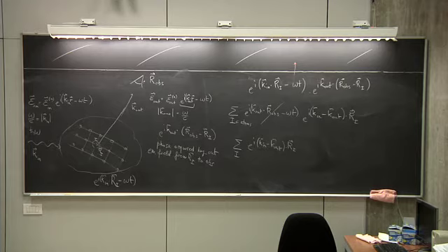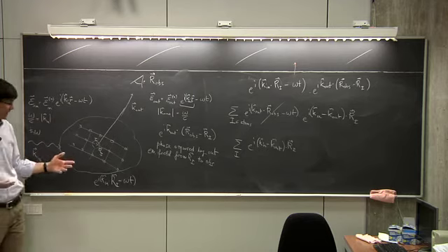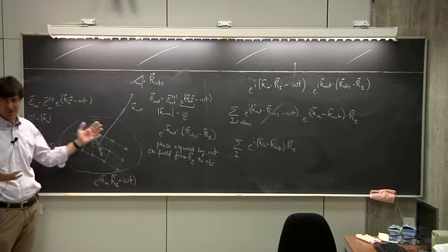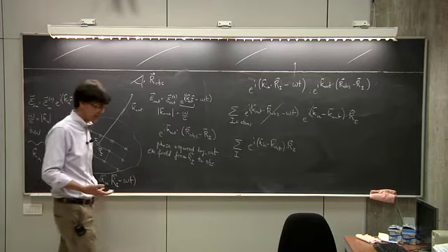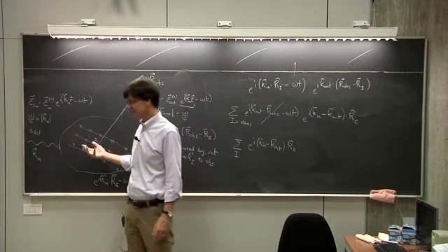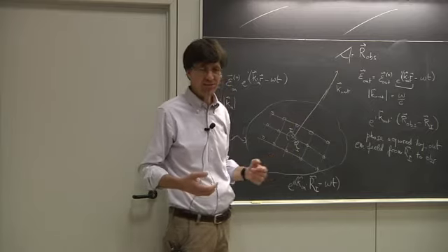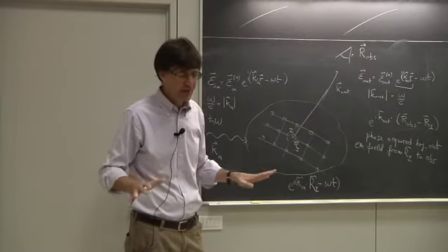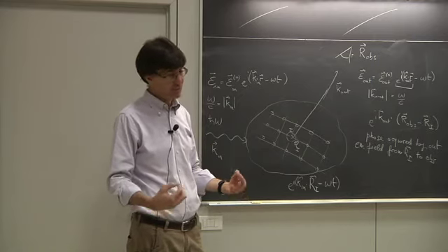What if there is correlation between the electronic states in this atom here and this atom here, and so on and so forth? What if we go to the extreme limit of free electrons? Free electrons don't even know that there is an underlying crystal, right? If you push that to the limit and say that your electrons are all free electrons, they don't know that there is an underlying lattice. So you'll never be able to extract information with X-ray diffraction, because the electrons will not tell you anything about what's below them, about where the nuclei are.